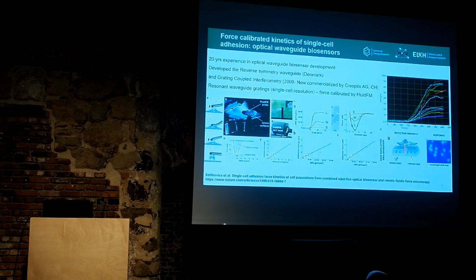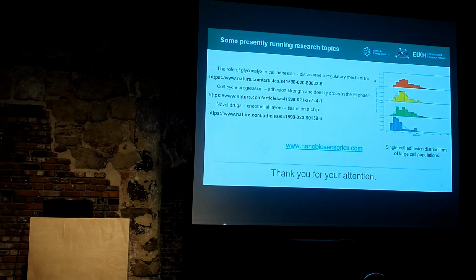And now we can calculate how much the adhesion force is at this time point, so everywhere on this curve. We are employing this technique in different topics, and just to show you some examples, we are investigating the sugar coat of cancer cells and discovered the regulatory mechanism for these sugar coats. The thickness of the sugar coat of cancer cells is quite thick compared to normal cells, and we could prove that it can control the adhesion strength. So it can even increase or decrease the adhesion strength by changing the thickness of the sugar coat.